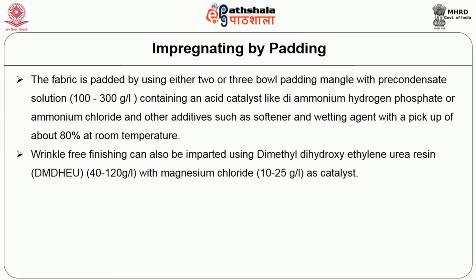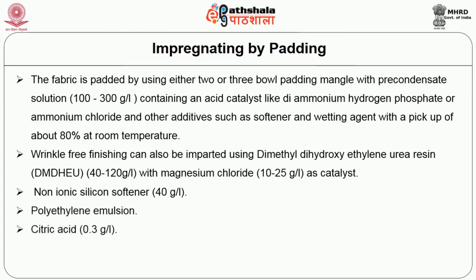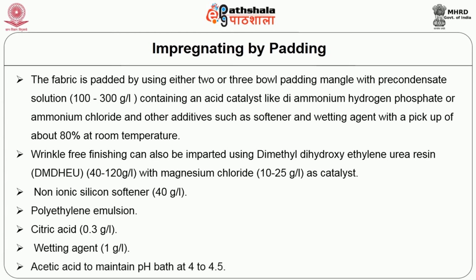Wrinkle-free finishing can also be imparted using dimethylol dihydroxyethylene urea resin 40 to 120 gram per liter with magnesium chloride 10 to 25 gram per liter as catalyst, non-ionic silicone softener 40 gram per liter, polyethylene emulsion, citric acid and wetting agent, and acetic acid to maintain the pH of the bath at 4 to 4.5.